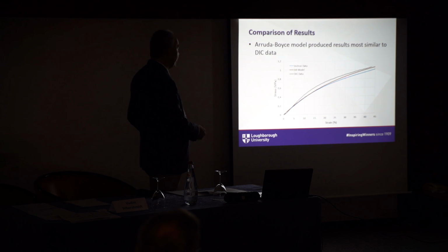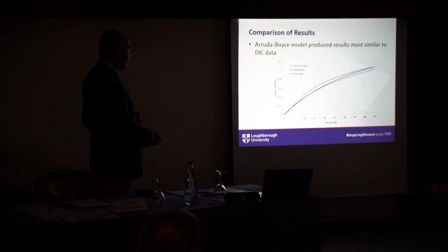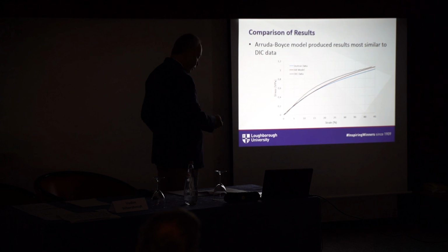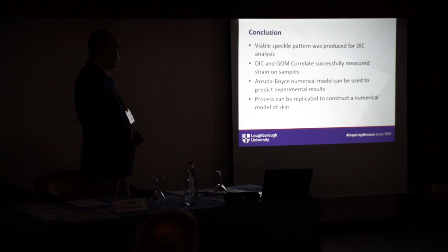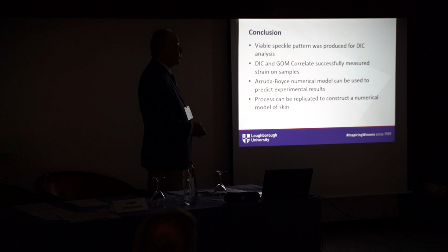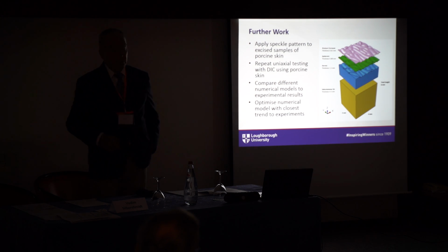You can see here the data obtained directly from the instrument and from the DIC. There is a gap, which is nearly constant at large deformation, and we have the Arruda model going pretty well along this line. Generally, there is no need to speak a lot about conclusions, but as I've said, this is the early stage of the PhD project, and the important thing is that we have got a reasonable way to deal with this. This is a preparation for the future work.